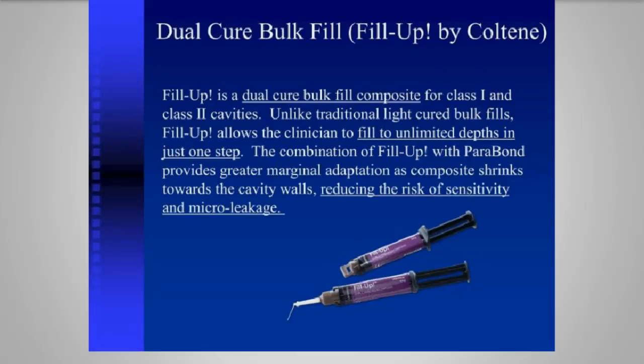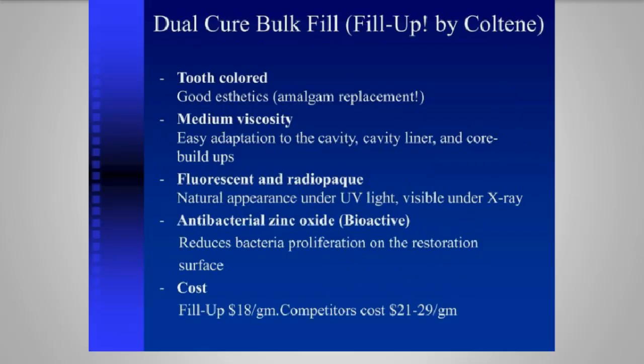The working time is 1 minute when you introduce the material out of the cannula. The set time, complete cure time, is 2 minutes. And like I say, once you put the light on the surface, you can start doing rotary finishing in 5 seconds. For those who are still using amalgam, it's a good amalgam replacement because it is a bulk fill material. It's medium viscosity. It's not too runny. I find the handling is very good. It's fluorescent. It's radiopaque. It actually is tooth colored.